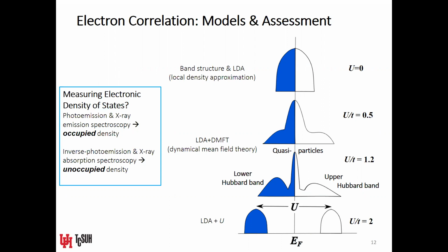If you want to take in more electron correlation and try to understand how electrons interact with their environment, you can apply the dynamical mean field theory model, okay? And that can be applied and has been applied, for example, when you have this non-zero electron correlation, okay? And so dynamical mean field theory will predict for you this kind of spectral weight. This is a density of states that emerges or gets changed as a result of adding more electron correlation. In the case of band structure and a simple metal, you have these blue states at the very top that represent filled states. And then immediately above the filled states, there are empty states. Those two are separated by some Fermi level, right?